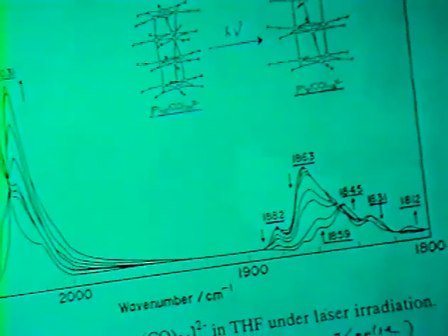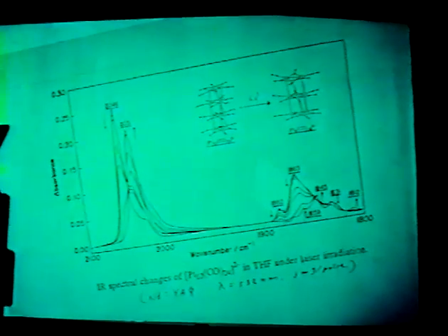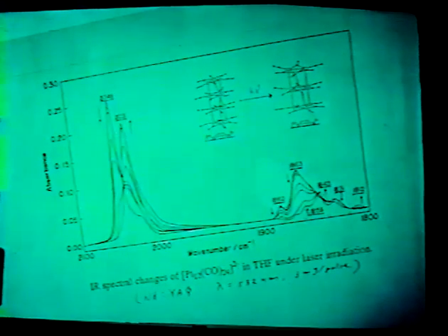This process proceeds irreversibly in the solution chemistry. But I would stress the point that this inter-plane platinum-platinum bond is very weak, so it is easy to step off with the topmost of the triangular clusters to eliminate, to make this point.